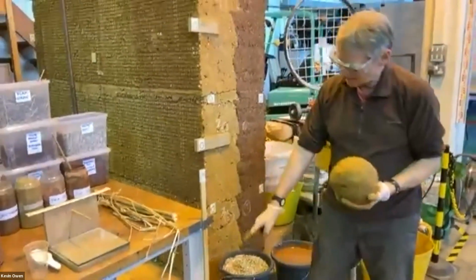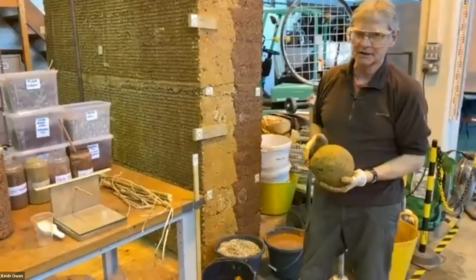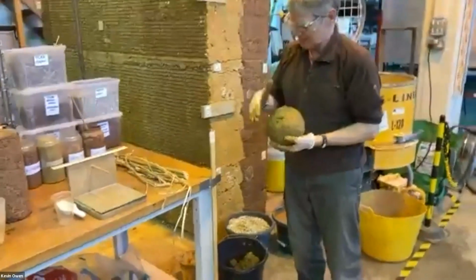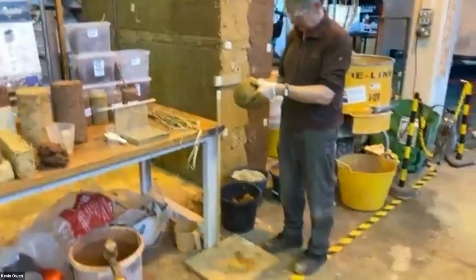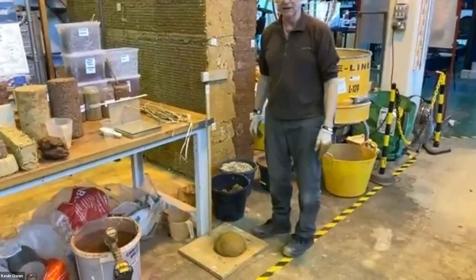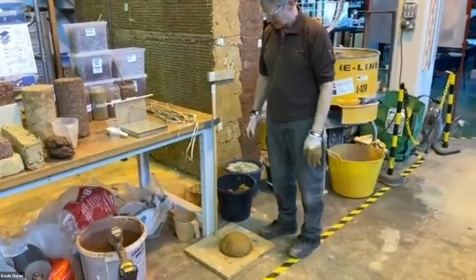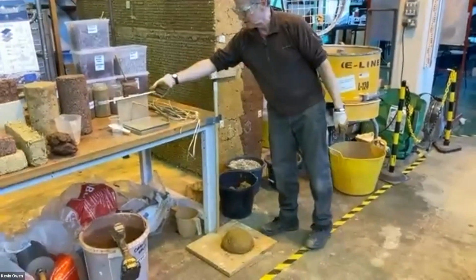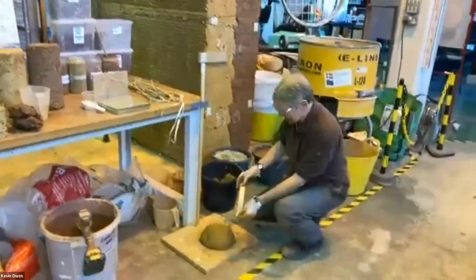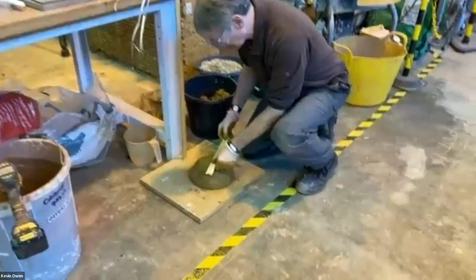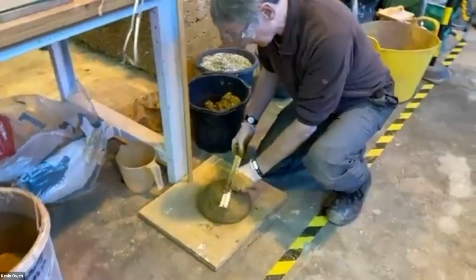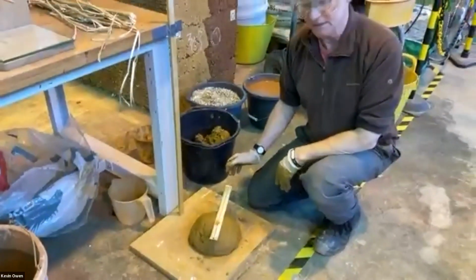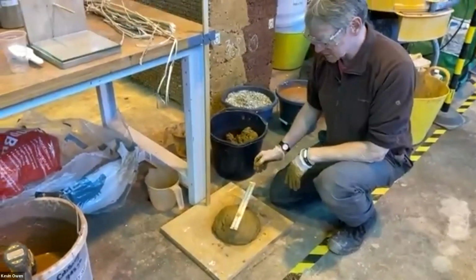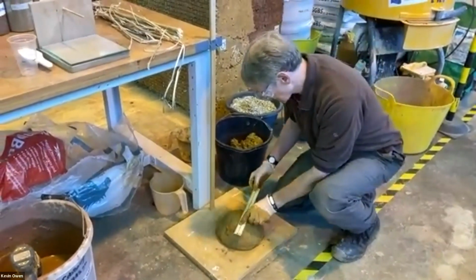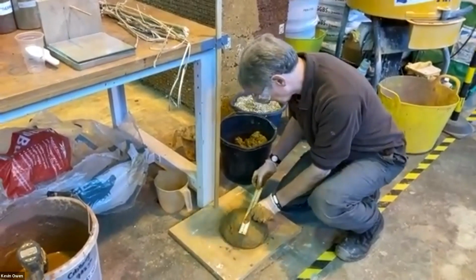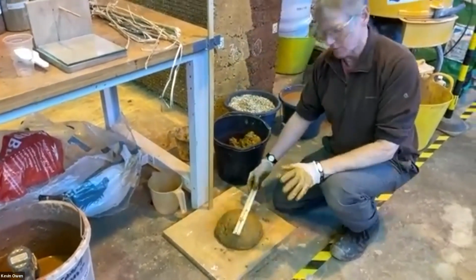So here I've got a stick with a 1 metre mark on it. If I drop this now from that height and let it hit the floor, we end up with a nice round splat. And all we need to do on site is just to measure that diameter. And we're looking for up to 21 centimetres. That will give an optimum mix. This one is just bordering on 20 centimetres, so that would be fine.